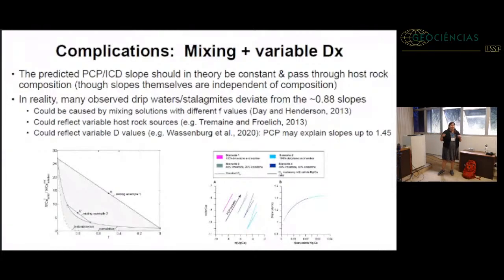So mixing lines can also affect or confound the trace element ratios that you're measuring. If you have solutions that have different flow paths and different amounts of PCP, so this is showing a PCP curve, this bottom curve here, for the distribution coefficient versus F, you can end up with these different compositions that have different Fs, and then if you mix them together, you can create a wide range of trace element signals.